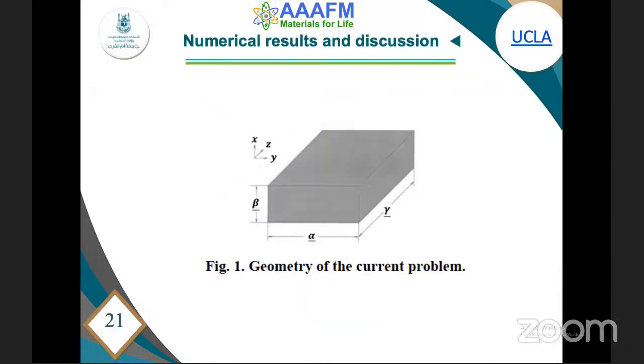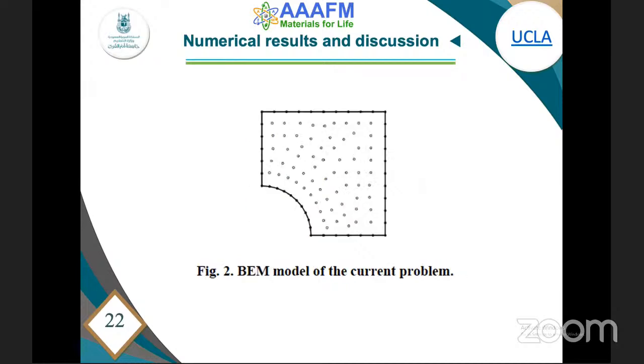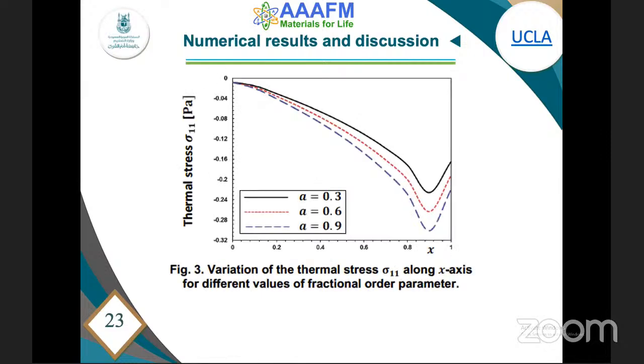Geometry of the current problem. Boundary element model of the current problem. This figure shows variation of the thermal stress sigma 11 along the x-axis for different values of fractional order parameter: 0.3, 0.6, 0.9. Variation of thermal stress with fractional order parameter.